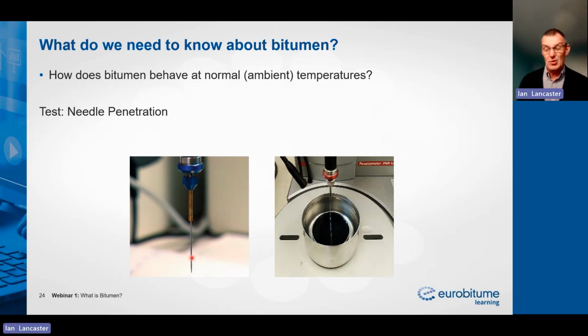We apply a load of 100 grams to the needle, and then we allow that needle to fall into the surface of the bitumen under that 100-gram load for a period of 5 seconds. And the depth of penetration, measured in tenths of a millimeter, is what we would call the pen value, or the pen number, or the penetration.